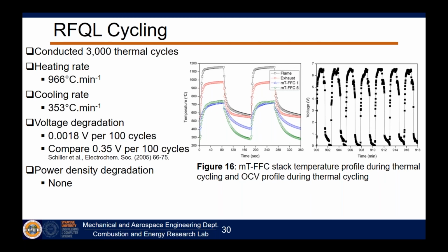Okay? And we cycled 3,000 times at a heating rate of almost 1,000 degrees Celsius per minute and a cooling rate of 350 degrees Celsius per minute. These give you a sense of the heating rate and the cooling rate. So these are the fuel cell temperatures right here. And over those 3,000 cycles, we saw about 2 millivolts per 100 cycle degradation. Compare that to about 0.35 volts per 100 cycles, which has been done in other tests. It's actually very, very low degradation. And we found that we had no degradation in power density, surprisingly, over those 3,000 cycles.